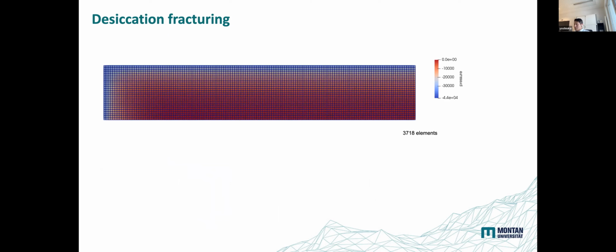And this is the simulation result of the fluid pressure first. As you see, near the boundaries, it developed negative pressure. That's when it loses the water saturation. Also, as you see, we use a very coarse mesh, only 3,700 elements in here, all structured elements, and the material properties were homogeneous. So in this model, in this domain, there's nothing to trigger any structure, right? The mesh is uniform, structured, and material properties are all homogeneous. So there's nothing that can trigger fracture development.